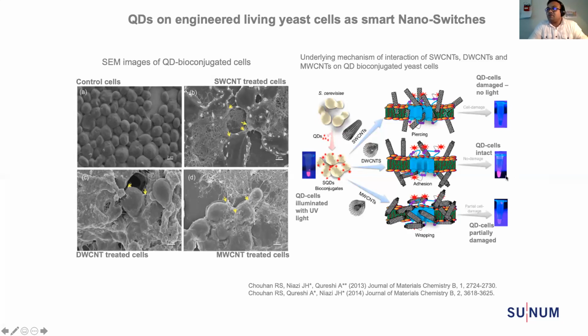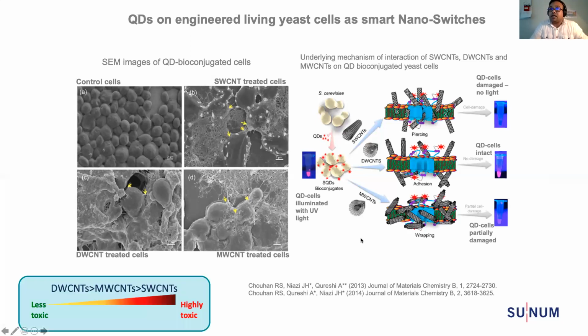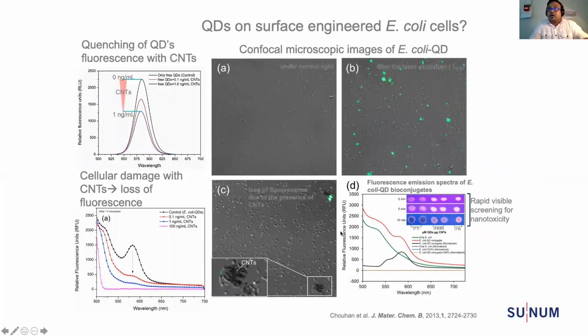So double wall carbon nanotube, for some reason, did not cause toxicity as much as it did in single wall carbon nanotubes. This we can easily see with our naked eyes. We also tried to do it with the bacterial cells. They are even faster growing cells. We can get it in maybe 5 to 10 minutes time. You can see these glass slide images, just like a blood typing type of test. You can actually see it with your naked eyes.